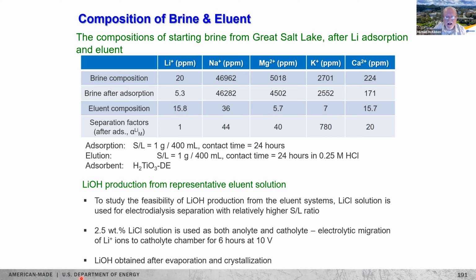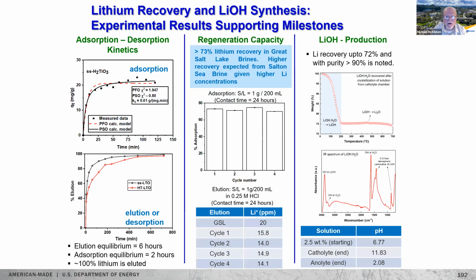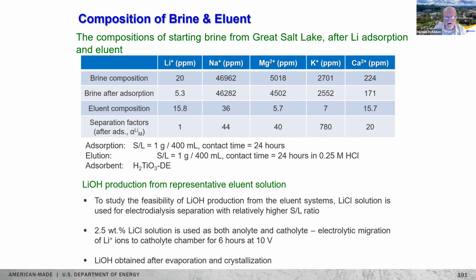Lithium chloride electrodialysis was conducted for 6 hours at 10 volts with a final lithium hydroxide product obtained after evaporation and crystallization. Next slide, please.